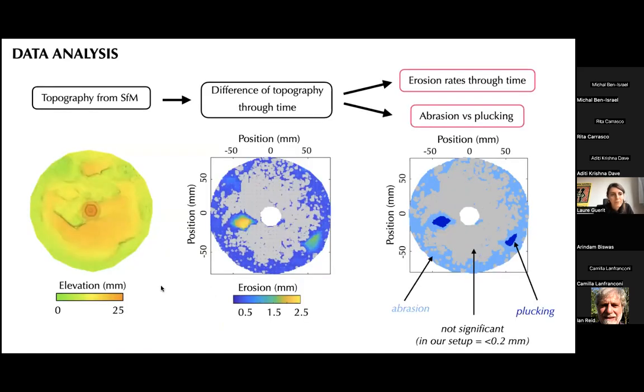So on the left, this is one example of the topography we can obtain with structure from motion in our setup. The color code is for elevation, and here in the middle, it's the screw that we use to attach the disc to the tube. In the other figures that I show, it has been removed.